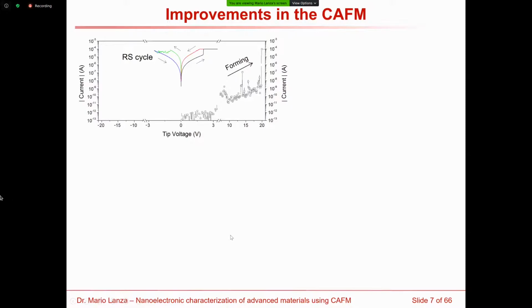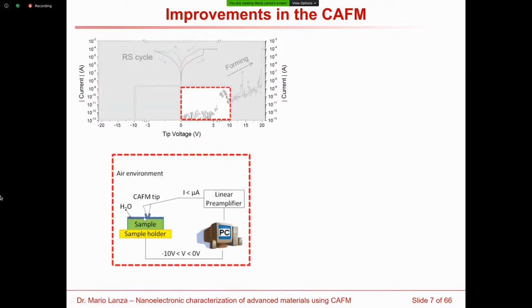You can see here the block diagram of one standard conductive AFM. And this is the window that you can measure. You can only measure currents up to some nanoamps. You can only apply voltages up to 10 volts. And you cannot measure both polarities, because if you are measuring in air environment, you have a water meniscus between the tip and the sample. And you can induce local anodic oxidation if you inject electrons from the tip. This is a problem of chemistry, but this is very well known in our field.